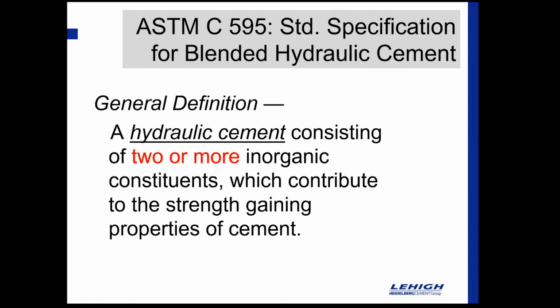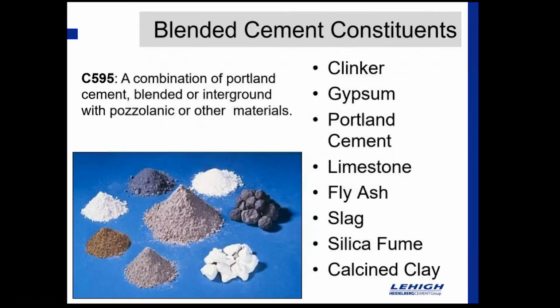Okay, so let's step into ASTM C595. That's the standard specification for a blended hydraulic cement. And the text definition says a hydraulic cement consisting of 2 or more inorganic constituents which contribute to the strength gaining properties of the cement. And so when we're looking at C595, we could be combining our clinker with gypsum, Portland cement, limestone, fly ash, slag, silica fume, calcined clay.